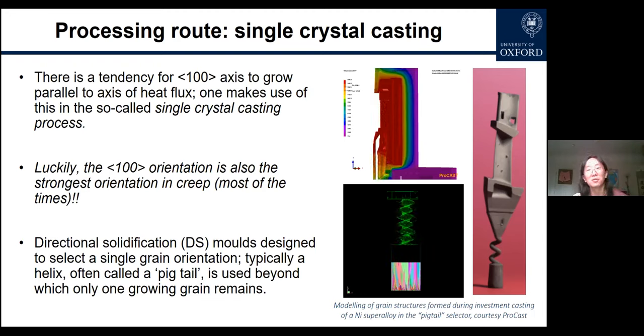Making single crystal alloys is similar to directional solidification, but now you have something different, called a pigtail or grain selector, where the grains grow through this grain selector initially, and these are very aligned to the 001 orientation. However, the fastest growing grain is going to eat out any other orientations.